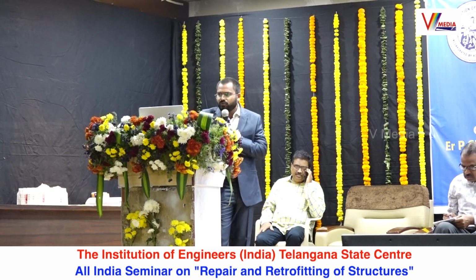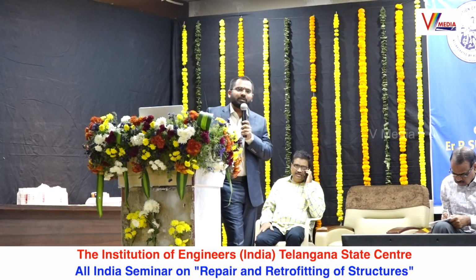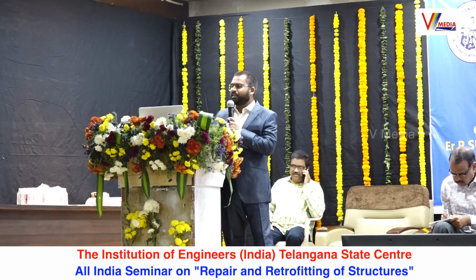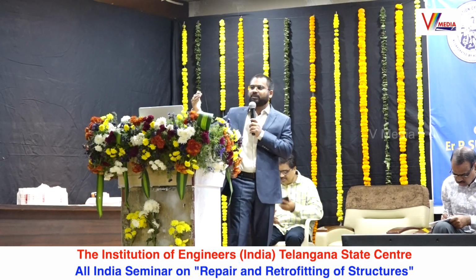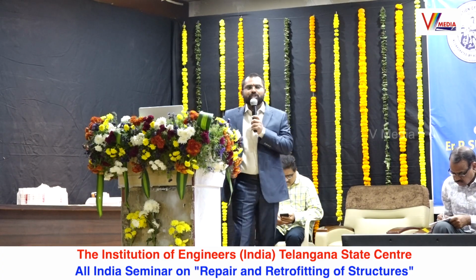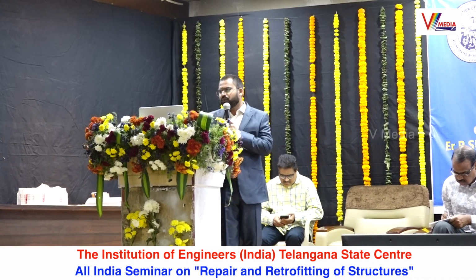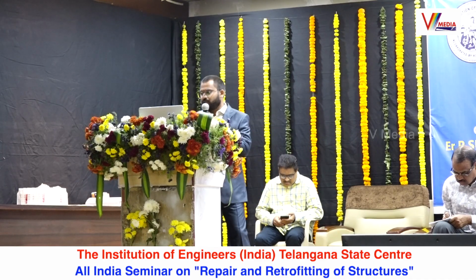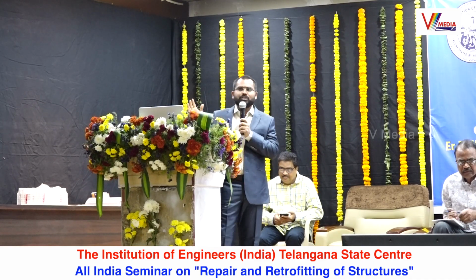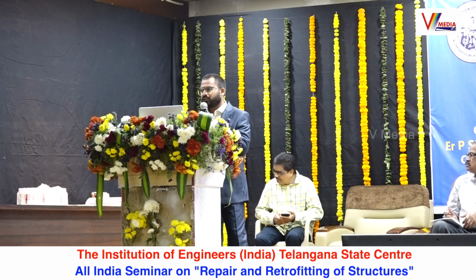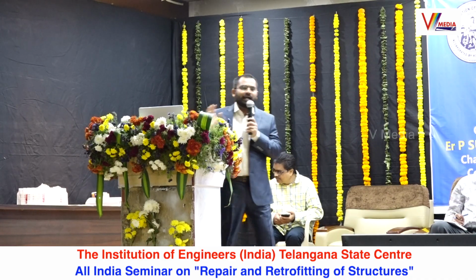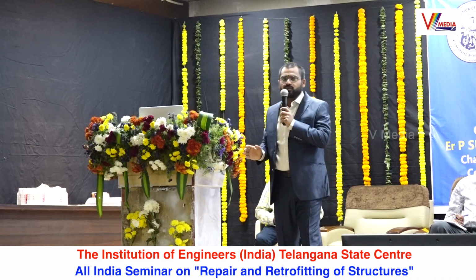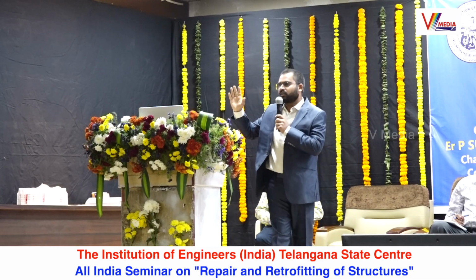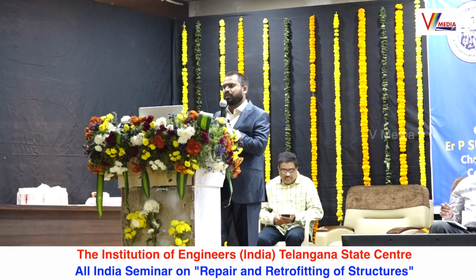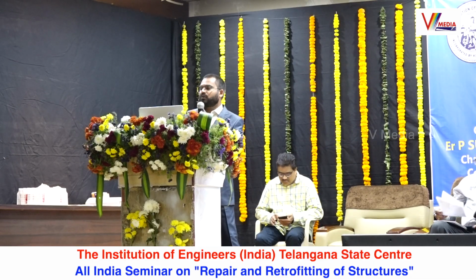So I will just show you the photographs of this rebound hammer test. You can do it in many directions. Horizontal is the best preferred way. You can see this is the position of the rebound hammer vertically upwards. This is the position of the rebound hammer vertically downwards. And this is the ideal position, I can say, the position of the rebound hammer in the horizontal method. I see in most of the projects, without chipping the plastering, the rebound hammer is done. It should not be done that way. Only the concrete element has to be tested.